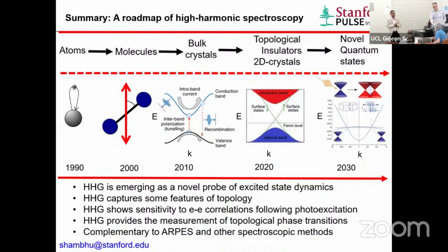Yeah, so actually, we did an experiment in the magnesium oxide crystal, and we basically looked at the polarization response, right? And the circular polarization also produces harmonics, as we expected in that sense. So yes, even in this semi-classical picture, you can rescatter from the nearest neighbor.